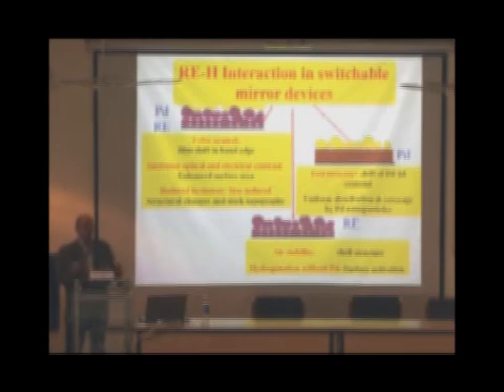Although I can say that there is a large improvement in the properties of the material, going from bulk to nanocrystalline or nanoparticle form, I cannot say what happens when they change the size because I don't have a size control. The size distribution of these nanoparticles is very broad. This is one of the limitations when you have a synthesis method where you don't have very good control of the nanoparticles. So the lesson is that we must have a synthesis method in which we are able to control the nanoparticles.